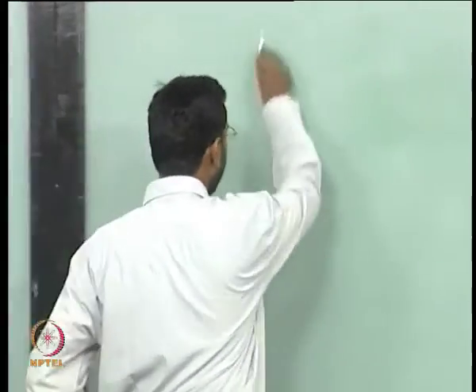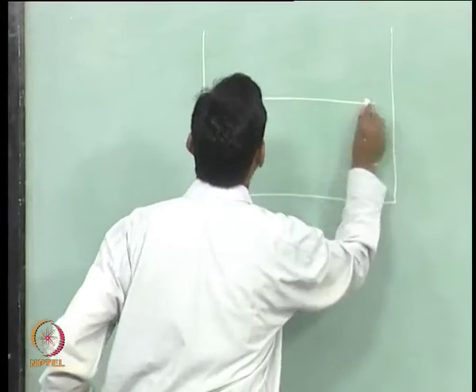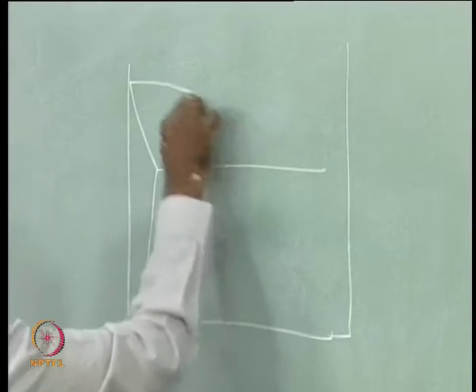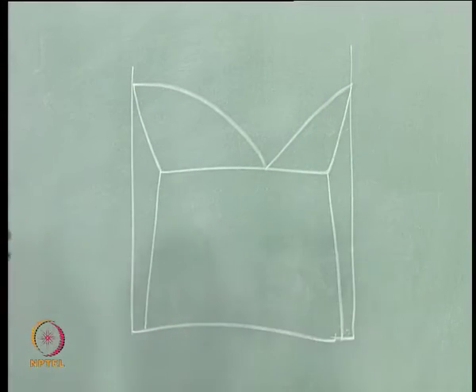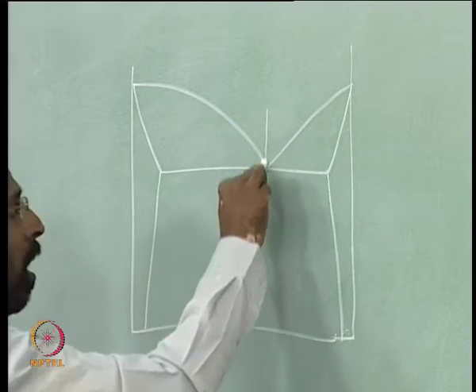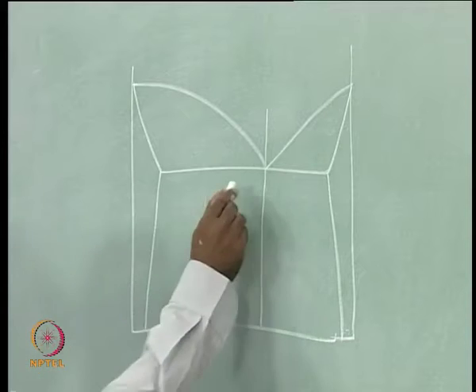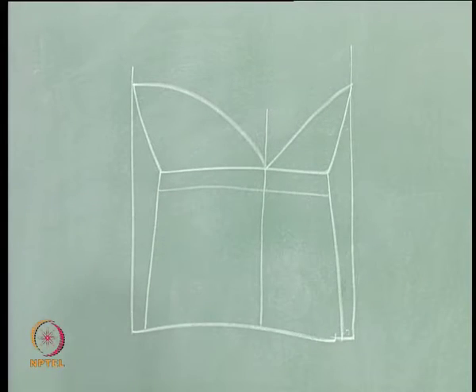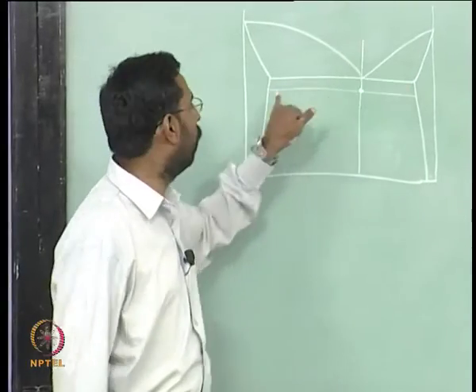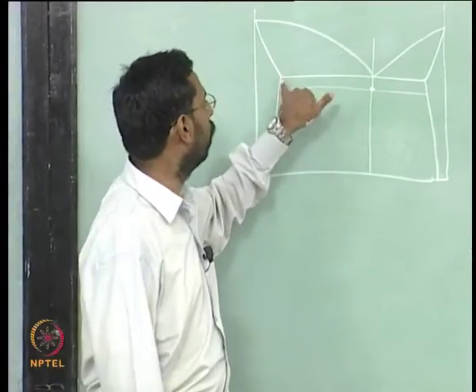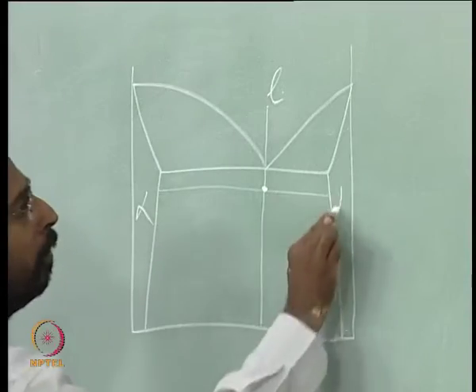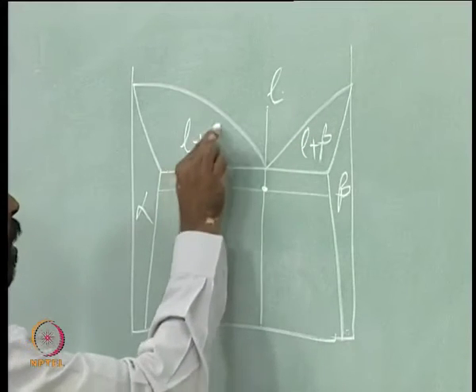For example, if you take a phase diagram like this, something like this, you take a eutectic composition, and the moment you come below the melting point, below the eutectic temperature, bring this liquid, hold it at this temperature, what should happen? Liquid should give you alpha plus beta, and this should happen by a nucleation and growth, isn't it? Because the liquid composition is different from the two solid compositions, whatever the two solid compositions are. So this is liquid, this is alpha, this is beta, this is liquid plus beta, this is liquid plus alpha, all this you people know.